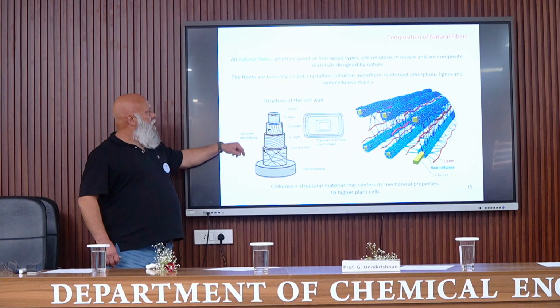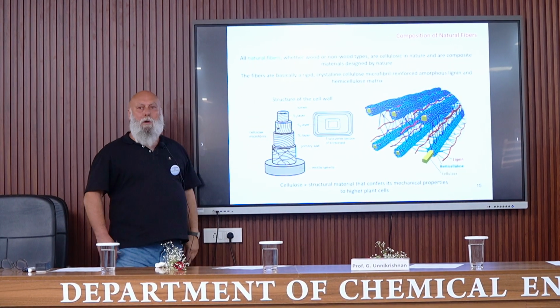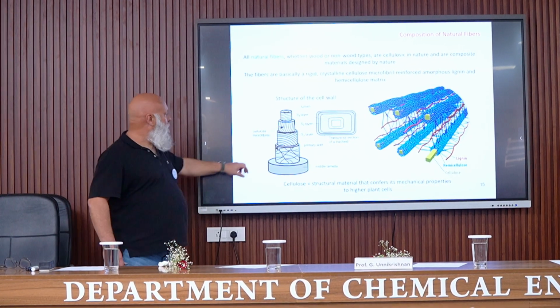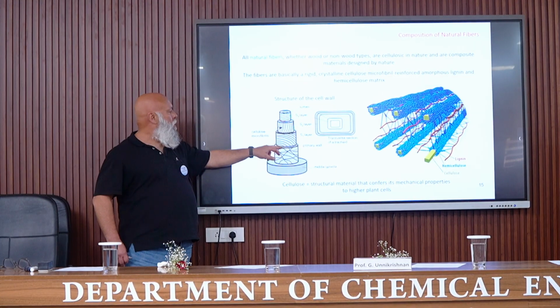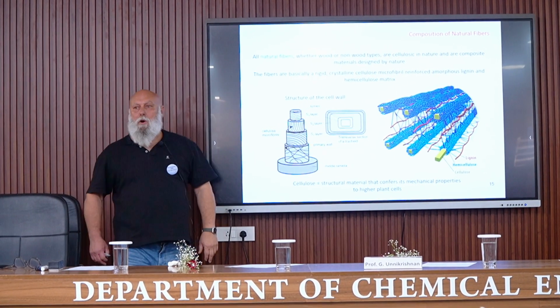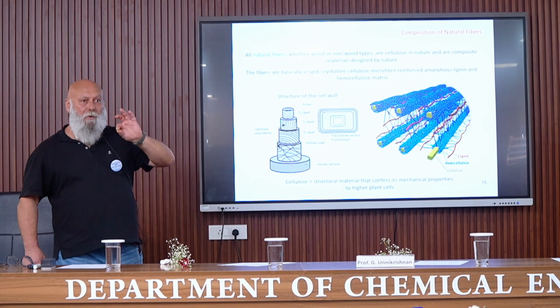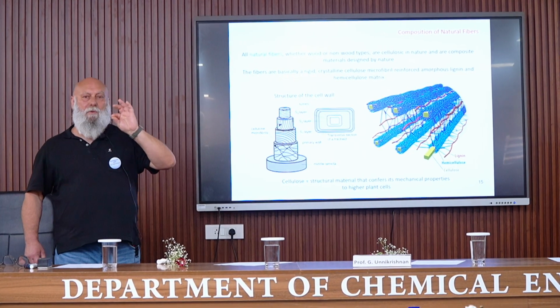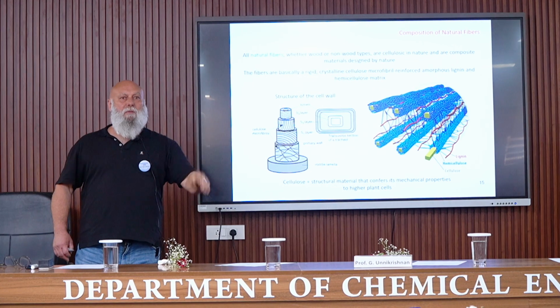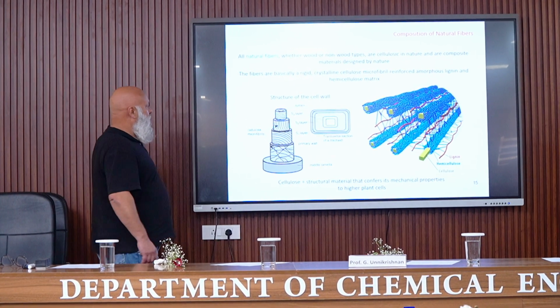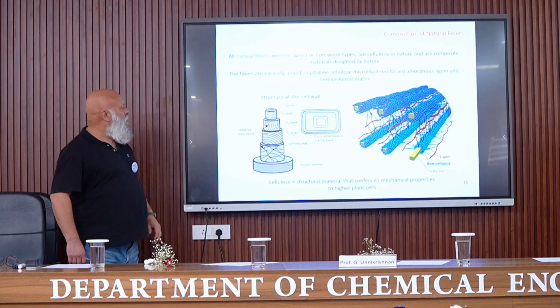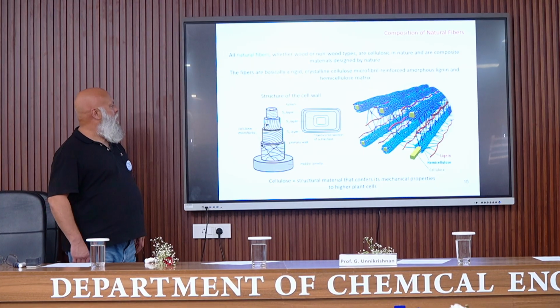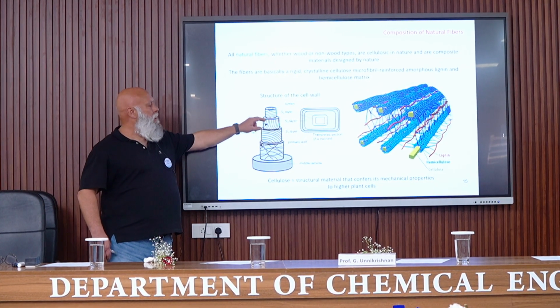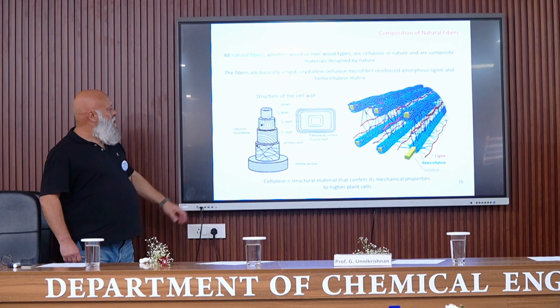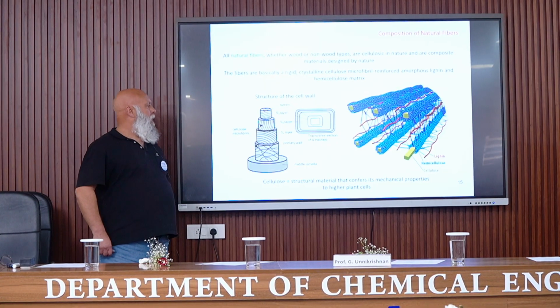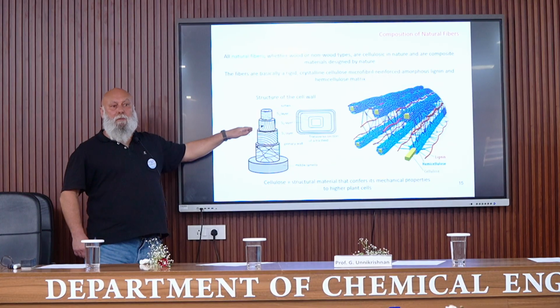So in this natural fiber, this is the structure of the cell wall, which consists of tubes. These tubes consist of what is called the primary wall, in which you can see a random orientation of cellulose in the form of fibrils. Remember, it's always important to have thin fibers or thin fibrils to have good mechanical properties. And then we find three other walls, which are called secondary walls, S1, S2, S3. The thicker one is S2. And you can see that in these walls, or in these layers, there is a given orientation of the cellulose fibrils.